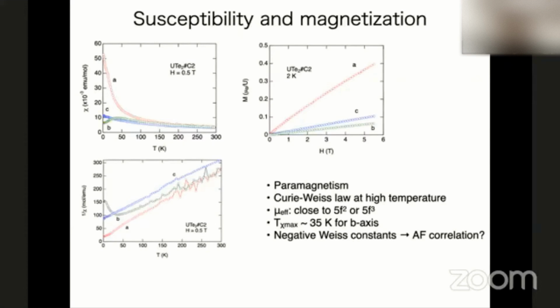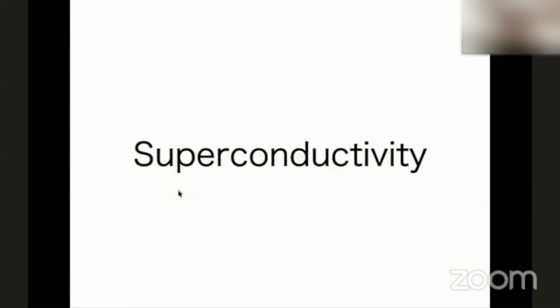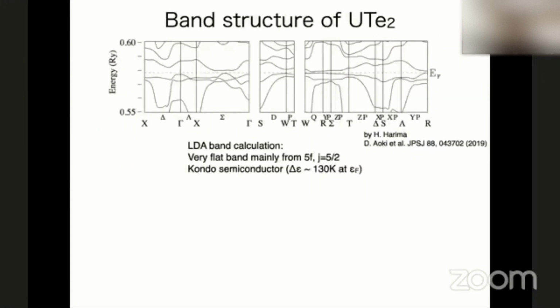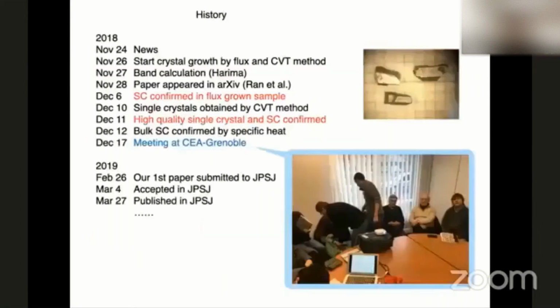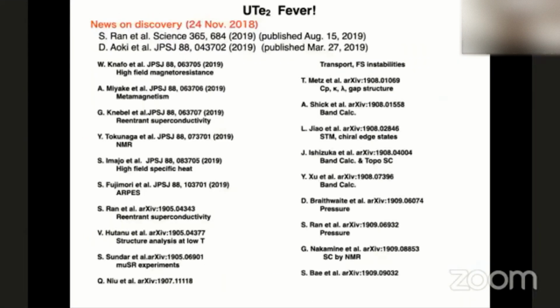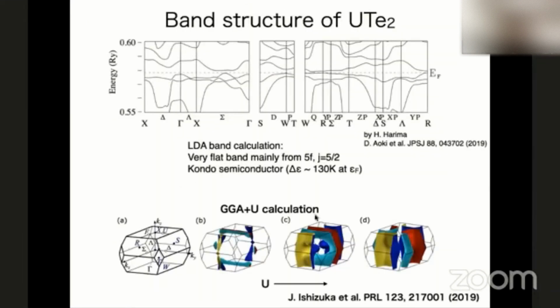In fact, it's an important point, because the important question is the Fermi surface of this material. Theoretically, if the U is large, quite strong two-dimensional Fermi surfaces are predicted like this here. But depending on U, it's more three-dimensional. For this reason, we had interest to measure the resistivity for J parallel a and J parallel c. And maybe, sorry, I can show you the